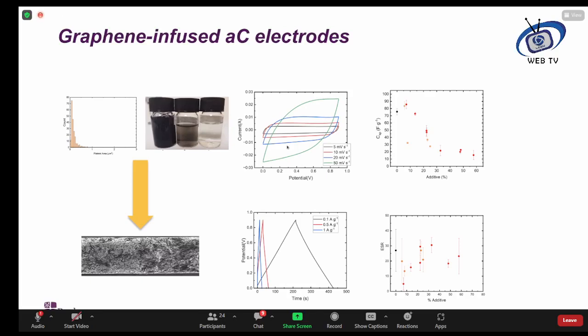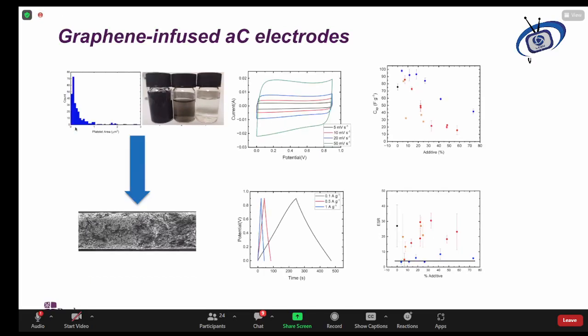So we went in the other direction. We chose a very broad distribution of platelet sizes. And we can see that, if anything, there is a further improvement to the shape of the cyclic voltammograms and to the galvanostatic charging and discharging. And you can see from the blue dots here that for every single concentration, we have improved performance. And particularly up here for relatively low concentrations, this is 7% of graphene to activated carbon, we have a considerably enhanced performance compared with other compositions. And this is also associated with a very good series resistance for all of the compositions of this broad distribution.